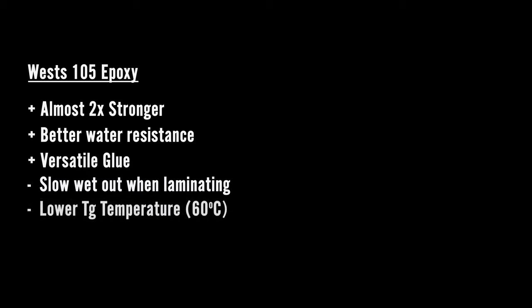Now, the disadvantage of using it for laminating is that even at the ideal temperature for application, it can take a lot longer, as we found, to properly wet out the cloth. Now, there are specialist laminating epoxies available which would speed this up, but as these are not readily available in chandleries, we decided that they were beyond the scope of this video. The glass transition temperature is the temperature point at which these composites start to soften, and with epoxy, it's quite low. For this reason, I avoid using epoxies in areas that are going to be painted a dark colour and exposed to direct sunlight, like the topsides on Black Sheep.